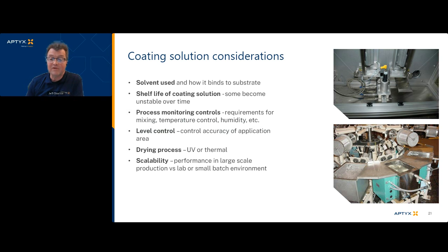From what I've seen from a material handling viewpoint, if somebody was selecting a coating that was either thermally cured or UV cured, the benefit I can comment on, only from a material handling viewpoint, is that UV curing is a much shorter period of time. Drying using thermal processes, usually lower temperatures and extended periods of time, can make the footprint of the machine slightly larger. It doesn't affect the throughput of the machine, because the throughput's based on the index rate. So if I'm indexing a set of parts every 2 minutes, every 5 minutes, that'll be my rate at which I get the parts out of the machine.